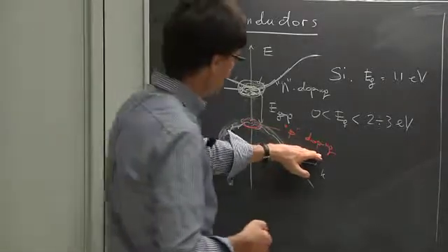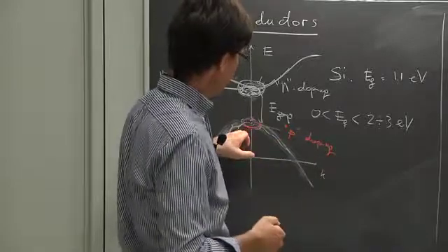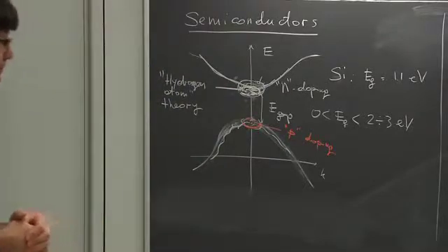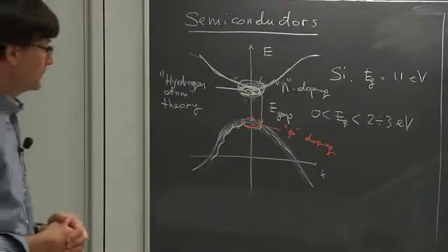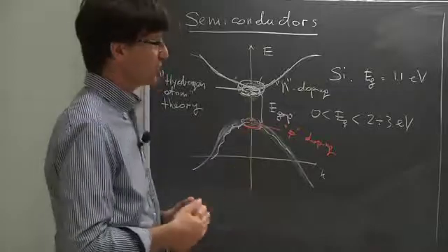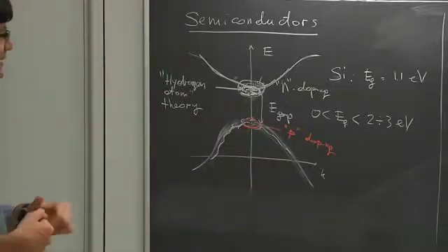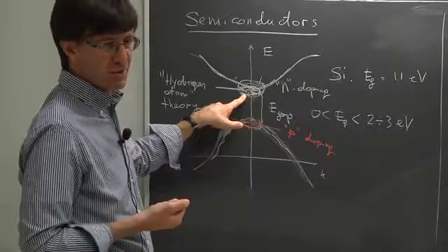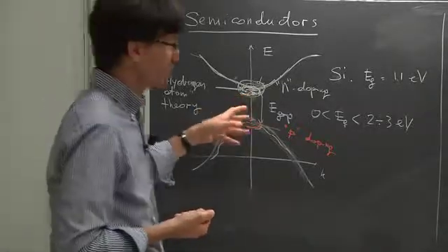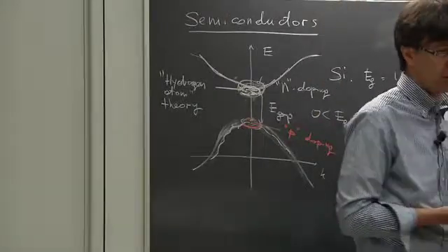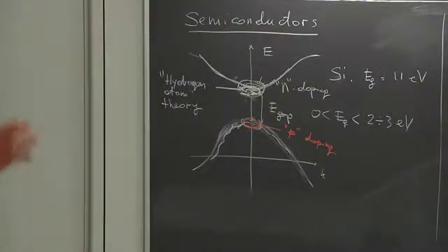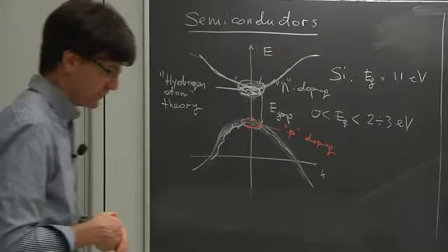Another important statement is that the number of carriers, electrons and holes, that you have here, oh, I'm calling them holes. I didn't introduce the concept of hole, but I will do it in a moment, is essentially independent of temperature now, because these are carriers introduced by a chemical process. They are not introduced by thermal excitation. So their number is essentially fixed by the chemical concentration.